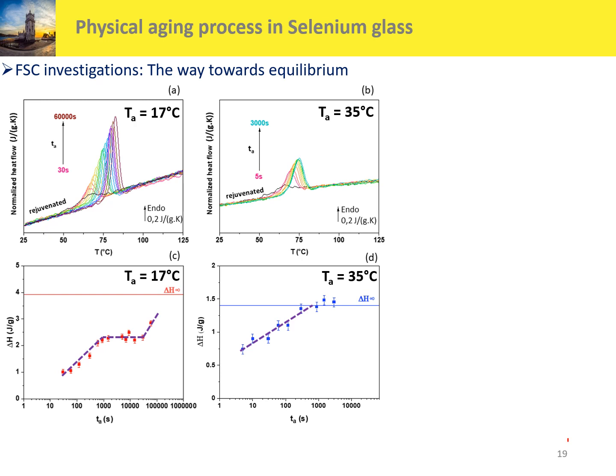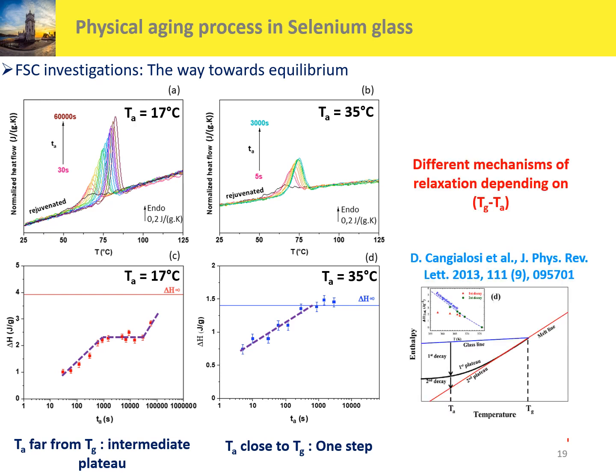We clearly observe different relaxation mechanisms. As shown here, for Ta far from Tg, we have an intermediate plateau, and for Ta close to Tg, we reach the equilibrium state in only one step. So we evidence different mechanisms of relaxation depending on the gap between Tg and Ta. And these results are in good agreement with the predictions of Cangialosi et al.